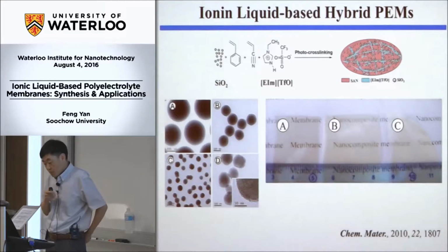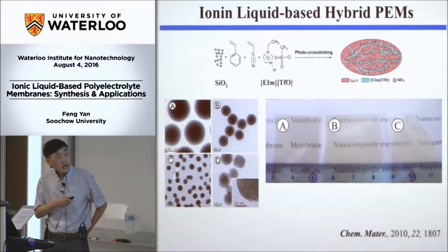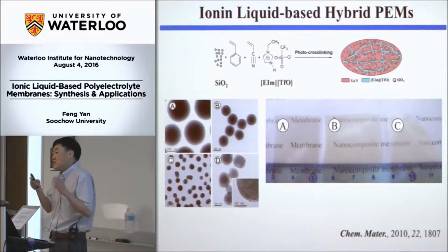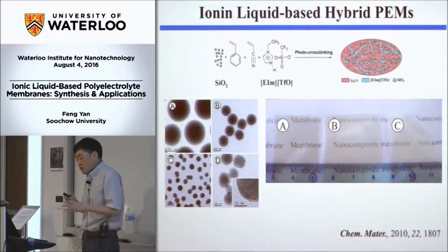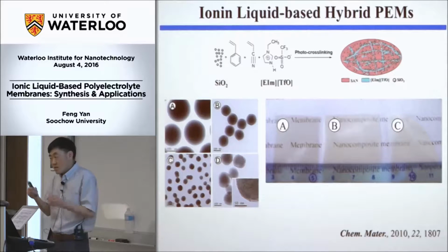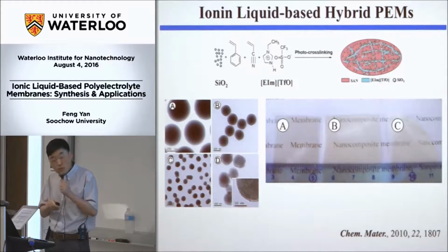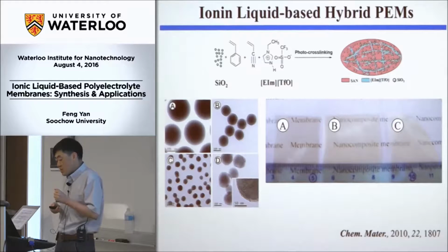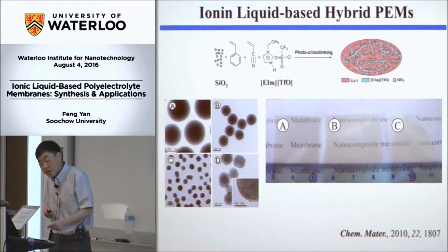One possible method is to add some inorganic nanoparticles inside this kind of membrane. We thought maybe the capillary force within the particles can retain the ionic liquid. So what we did, we synthesized this kind of composite membranes, and then we dipped the membrane into water.